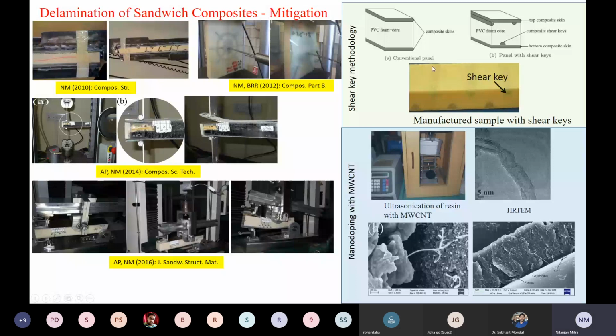And then we can also do something with carbon nanotubes. If you put carbon nanotubes, they form some kind of chains, and that prevents the crack from forming. So these are two different methodologies, at least what we have worked on. There are obviously other methodologies, one of them being stitching. We have not worked on that. So by these two methodologies, we can prevent delamination.